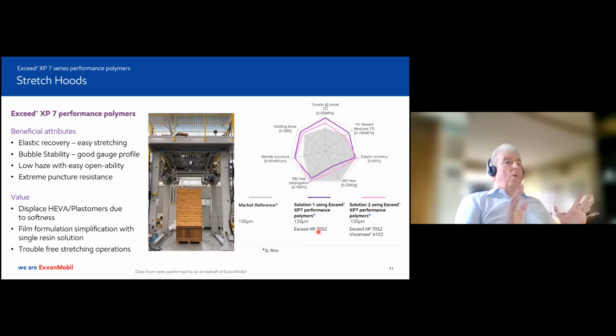Now, where extra elastic recovery is needed and better snapback, then the addition of a softer blend partner in the core, such as our Vistamaxx 6102, is recommended. And I would say most people are leaning more towards this pink one. But you can see that we've now really transformed our previous offerings in the marketplace in stretch hood to something that can be used in all layers with the possible addition of a blend partner in the core.